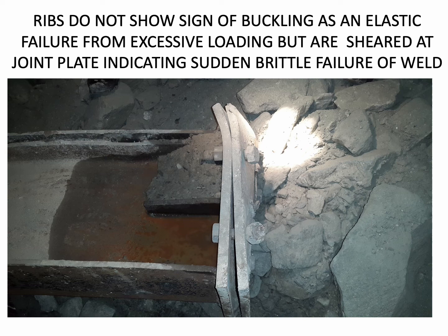This shows a sudden brittle failure. Ribs do not show sign of buckling as an elastic failure from excessive loading, but are sheared at the joint plate, indicating sudden brittle failure of the weld. So the weld between the rib and the connecting plate had failed because of the sudden brittle failure, and there was no sign of yielding under any load which would have shown any twisting or yielding of the ribs.